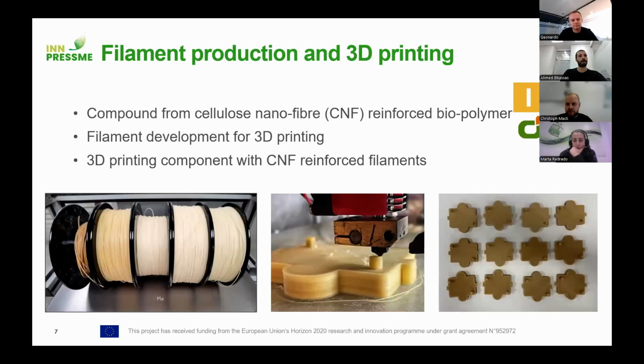When we come to the 3D printing, we used cellulose nanofiber reinforced PLA, which was provided by VTT and compounded by CEA. The filament was developed for the 3D printing, and in the end, those CNF reinforced filaments were printed into components. In this case, it was a holder for a data logger, for example, to log or track the temperature inside of a thermal box.